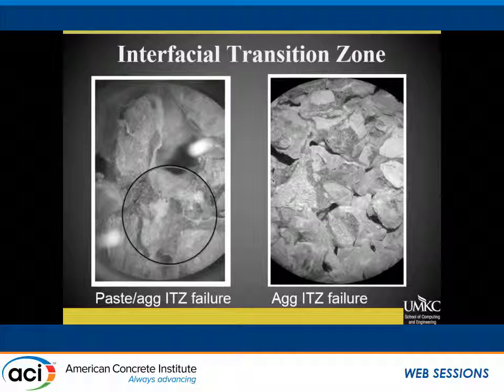So if we looked at, for our river gravel, paste aggregate, here's a shot of our control with the river gravel, and we had plenty of cups. So the aggregate pulled right out; in strength testing, we had plenty of aggregate paste bonding failure. And here's our 5% sample, and the majority of those were broken through the aggregate, so we could say that we probably had some ITZ improvements in our paste aggregate bonding.